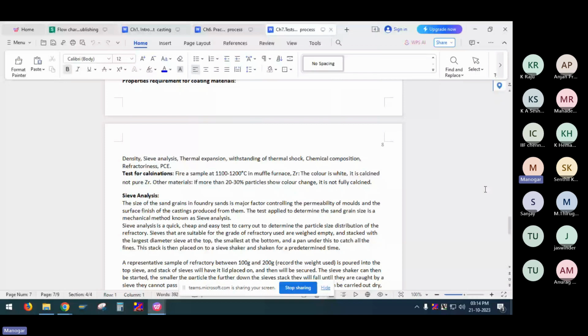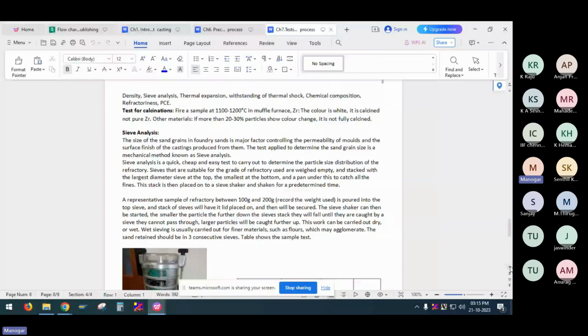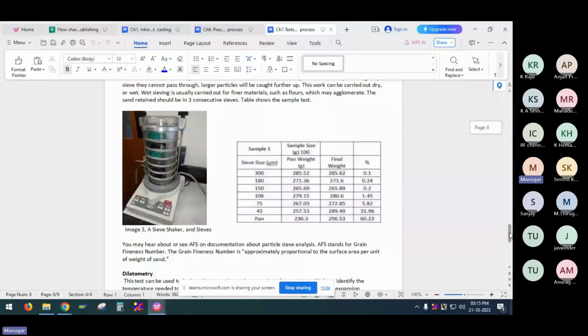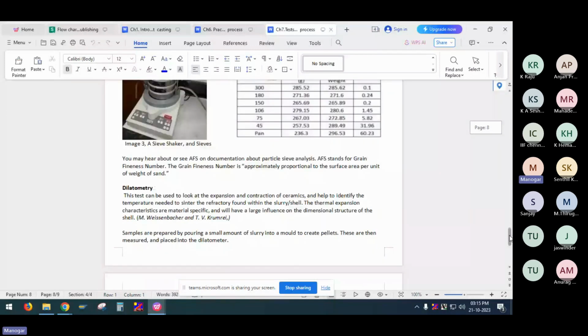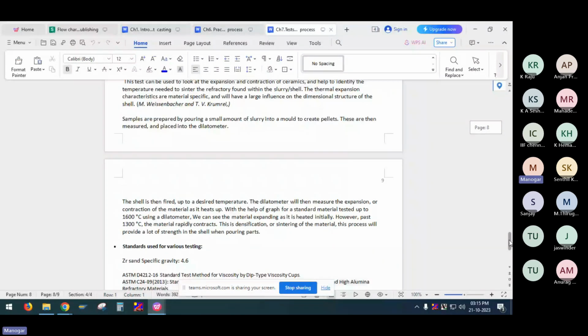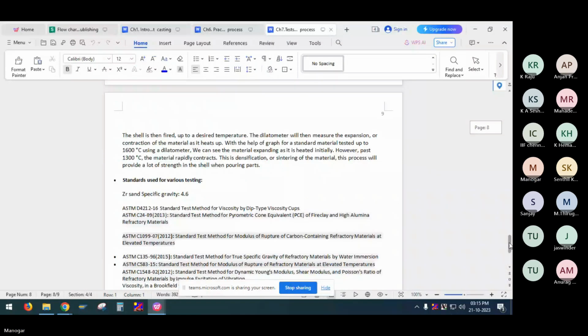Sieve analysis is the same sieve analysis that we do for sand foundries. The only difference here is that the grain size varies from 300 mesh to 20 to 40, so you have to test different materials depending upon the requirement. Same procedure and same thing as in other foundries for sieve analysis. And then the standards for various testing of the materials.